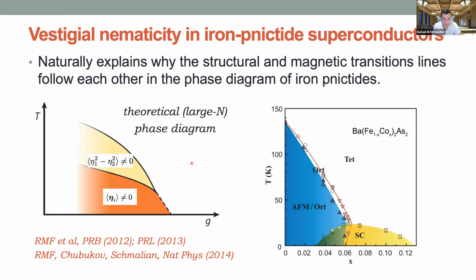I'm not going to give you any technical details, but you can write down your theory of free energy in terms of the etas, and you can do beyond mean field calculations. This is the result of a large N calculation, which includes fluctuations in a self-consistent way, which actually also agrees with renormalization group calculations. You get this split transition where you break the tetragonal symmetry, and another one where you go to the magnetic phase. They follow each other, and then they actually merge in a single first order transition.